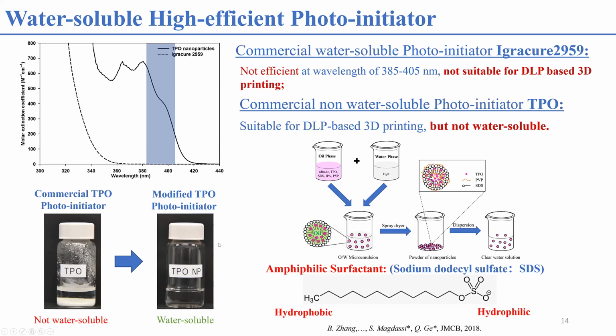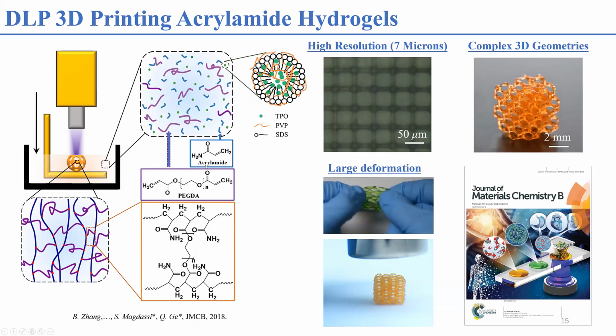Therefore, we can print a hydrogel system, such as an acrylamide-based hydrogel system, which has high water content, more than 90% water. And having such a hydrogel precursor, we then use DLP 3D printing. We can print a high resolution hydrogel network. The width of the grid is down to 7 micron, and we can print a very complex 3D structure, such as a carbon foam. And also this hydrogel exhibits excellent mechanical property. It can sustain a large stretch or compression.